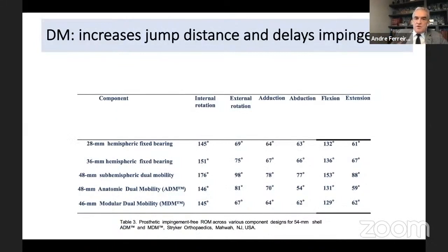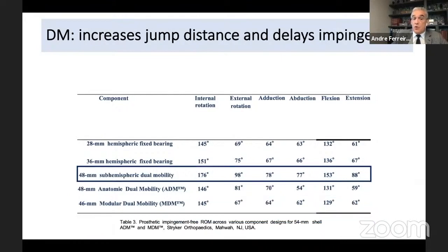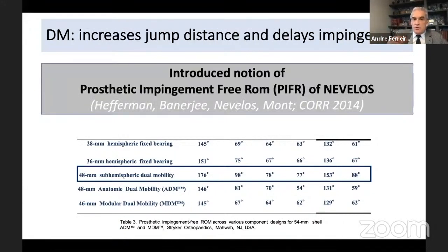At the same time, if we consider the free ROM of the cups and, of course, of the dual mobility ones, with the risk of impingement, we can see that if we consider some dual mobility cups, hemispheric, subhemispheric, anatomic ones, the ADM of Stryker, or modular dual mobility of Stryker 2, in comparison with the standard cups, about the abduction, there are very different results according to the design. And then for the flexion, it's exactly the same. We can see that the subhemispheric dual mobility cup has the best results. That means that if we delay the contact between the neck and the shell, we delay the risk of dislocation. That introduced the notion of prosthetic impingement free ROM of Nevelos.